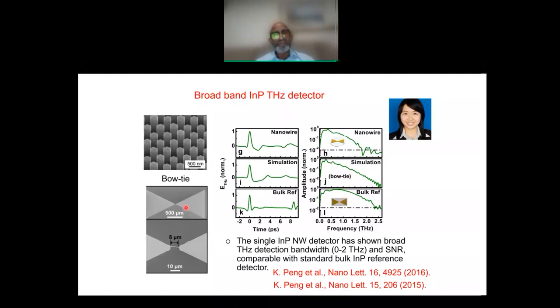You can see she creates something called a bow tie antenna, and then we have this nanowire sitting in between the bow tie, for example, here. You can also see that you get very broad bandwidth detectors, and the simulations and experiments are very much comparable. And these nanowires are as good as the bulk reference detectors which people have been using in the industry.